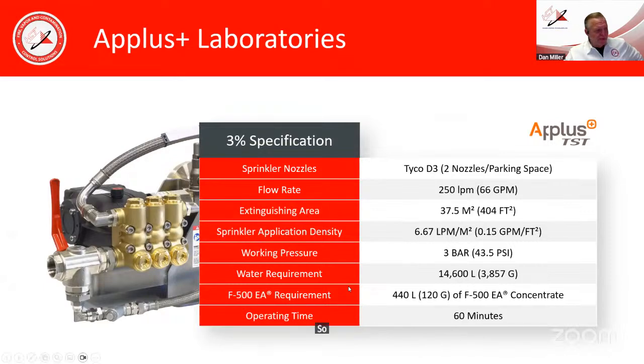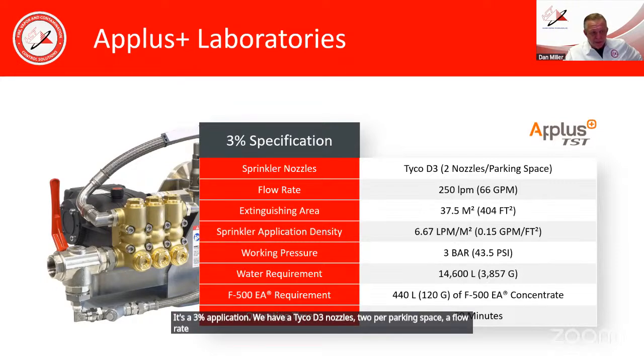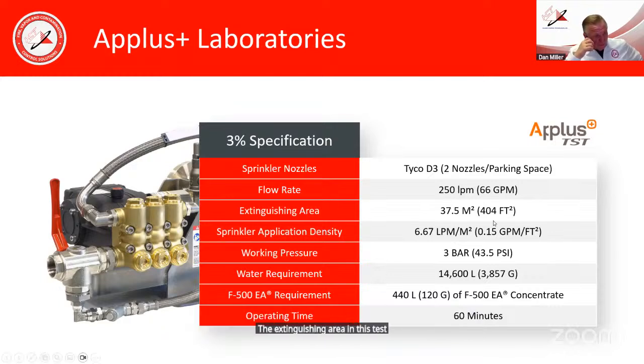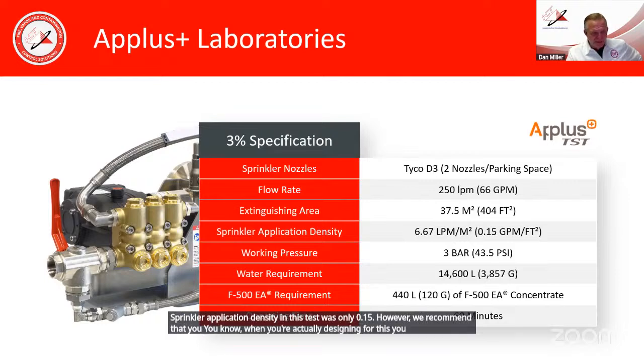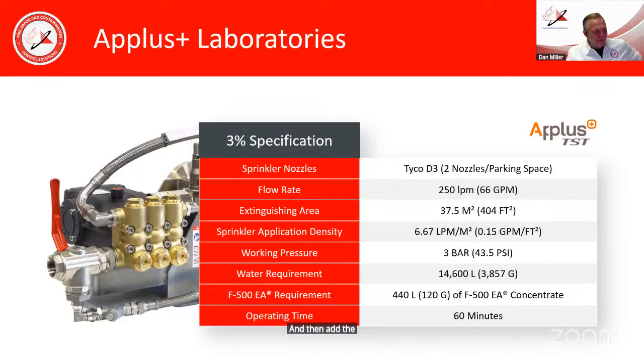So part of this system, if you look at some of the components involved, it's a 3% application. We have Tyco D3 nozzles, 2 per parking space, a flow rate of 250 liters per minute, or only 66 gallons per minute. The extinguishing area in this test was 404 square feet, or 37.5 square meters. Sprinkler application density in this test was only 0.15. However, we recommend that when you're actually designing for this, you design the system to either the NFPA or FM requirements, and then add the F500 at 3% because it'll more than do the job.